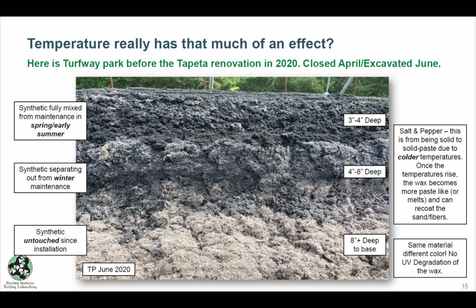You can see that no degradation of the wax has occurred because the material's not touched or mixed. We don't have any of that carbon black material leaching out. But you can see that there was no separation there, and that's just because the track was never touched. But we do have temperatures affecting the track in such a way that you can visually see the differences going on.